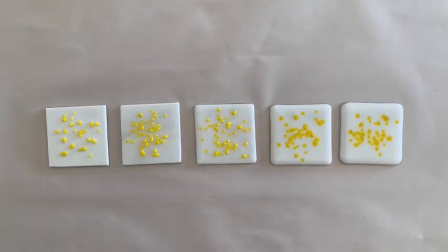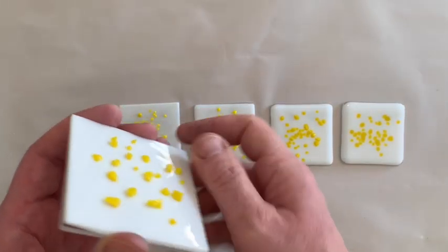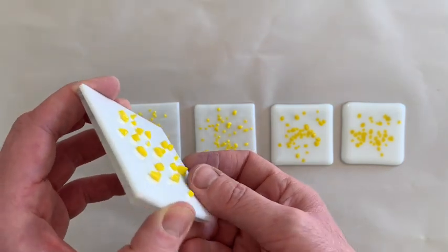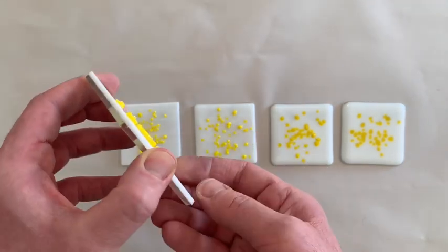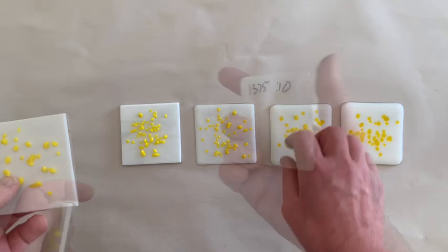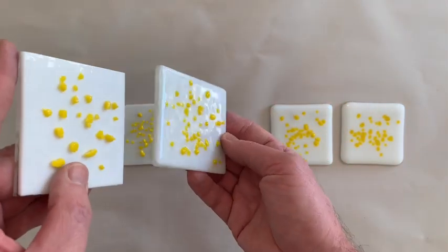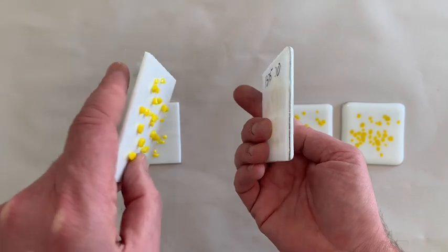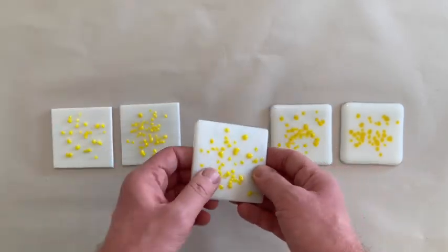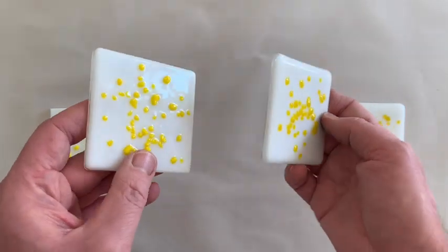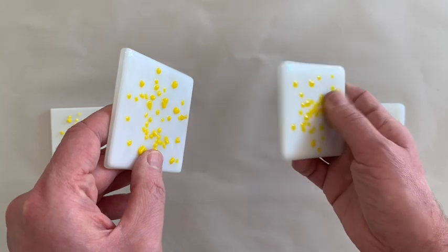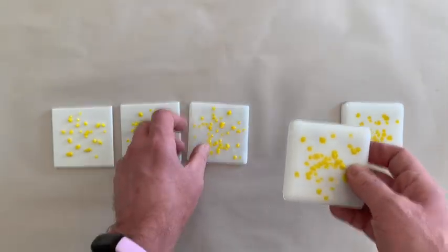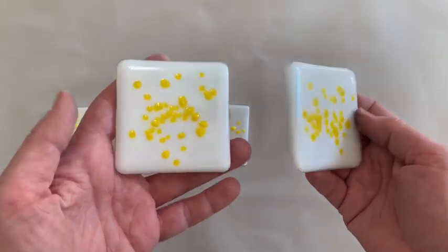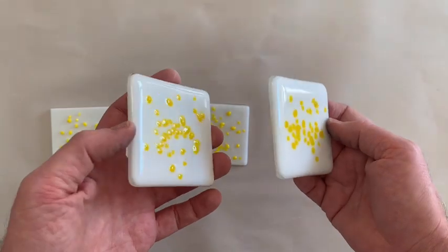The coarse frit samples follow the same results. At 1265 degrees Fahrenheit, the coarse frit remains fairly jagged. At 1375 degrees, the coarse frit is much more tacked and glossy. At 1420, the tack fuse is less pronounced, but still raised. And at 1460 degrees Fahrenheit, the materials are fully fused.